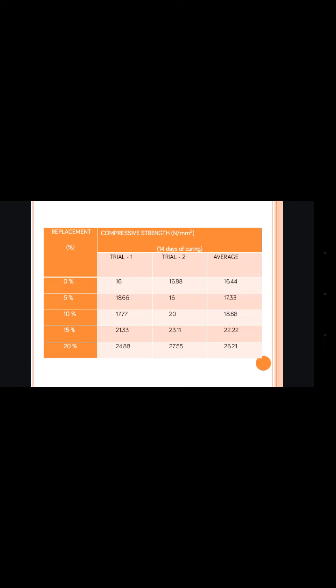So these are the details of the compressive strength test. You can see the 0% replacement is nothing but the standard cube without any kind of replacement. This tabular column shows the 14 days curing of concrete, trial 1 and trial 2, and average. From this tabular column, we can find that as the percentage replacement increases, the average compressive strength also increases.